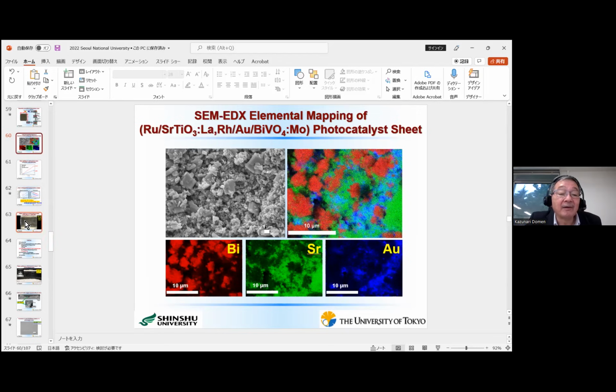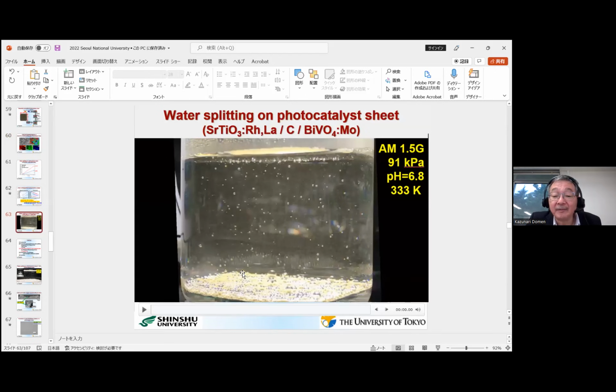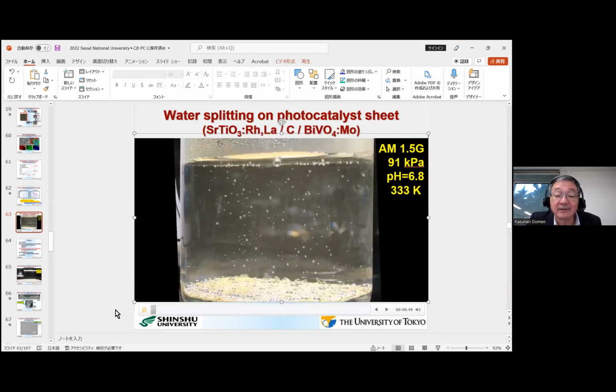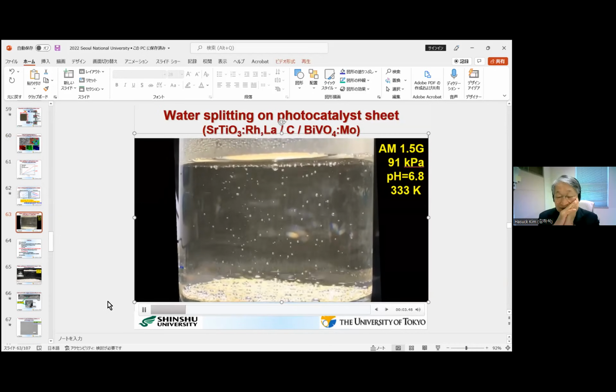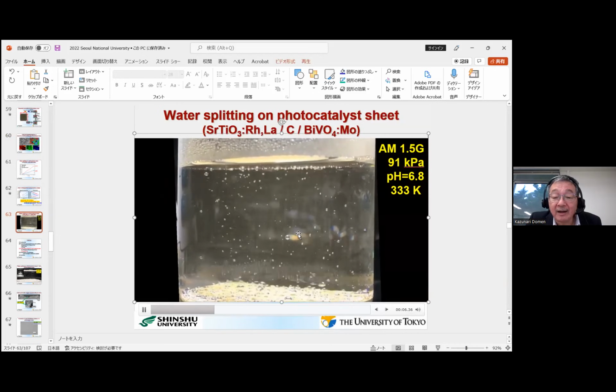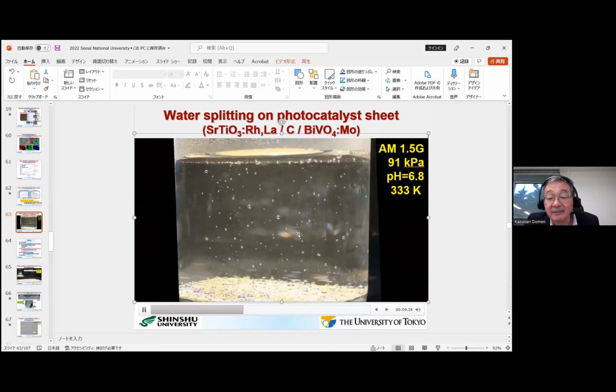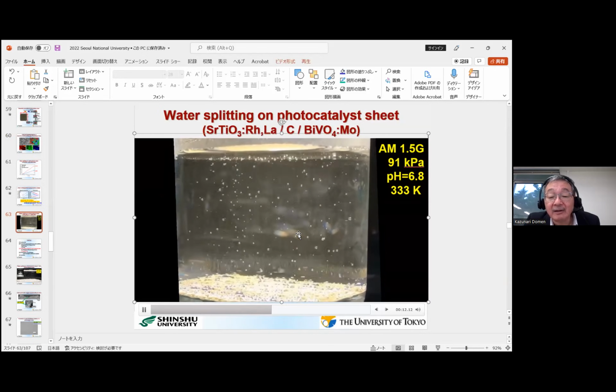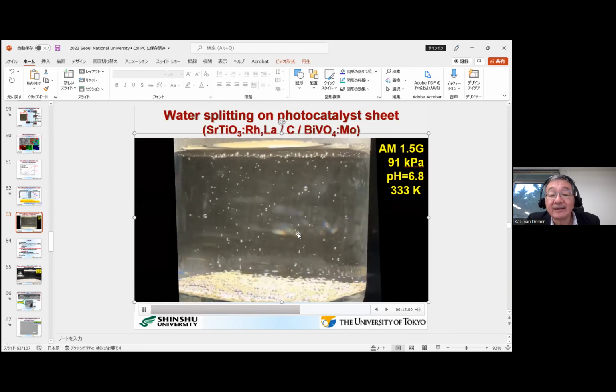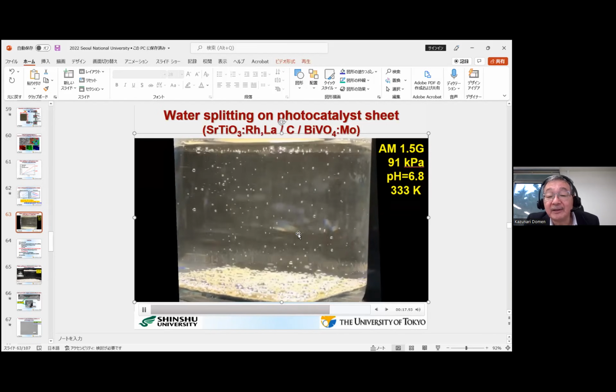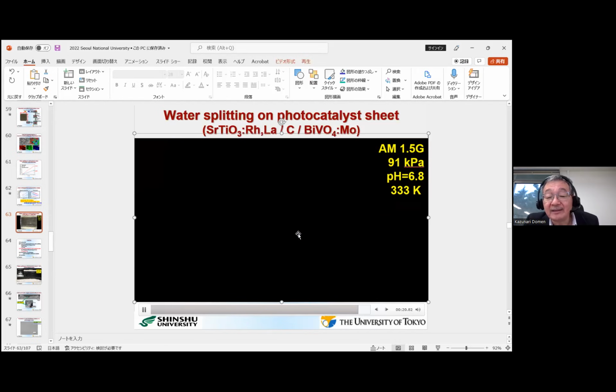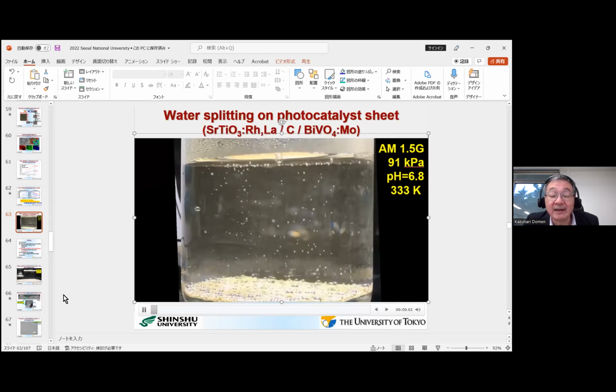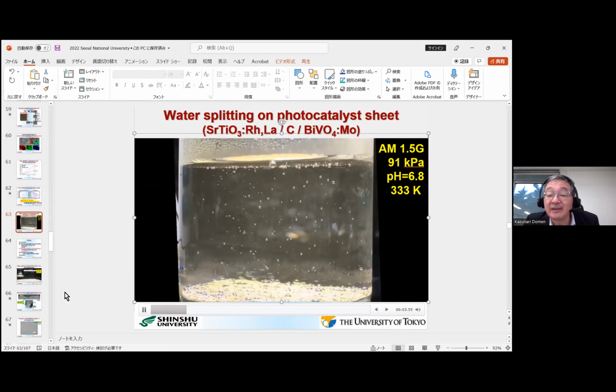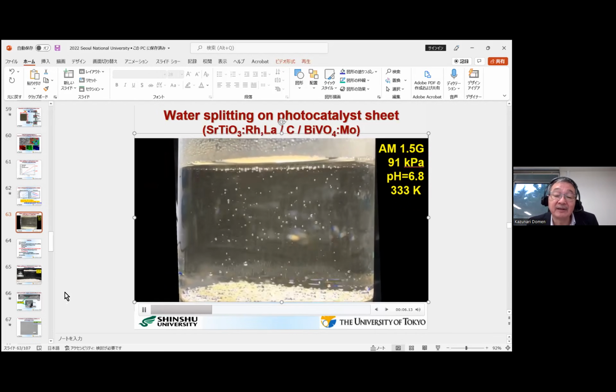Oh, okay. For example, in this case, as you see, both hydrogen and oxygen are evolving. We use just distilled water, and both hydrogen and oxygen evolve exactly in a 2:1 ratio. The pH doesn't change, so we don't need to control the pH. Always the pH is about 6.8. That is because our system contains some amount of gas phase carbon dioxide, so the pH is about 6.8, and the pH doesn't change even as the reaction proceeds.